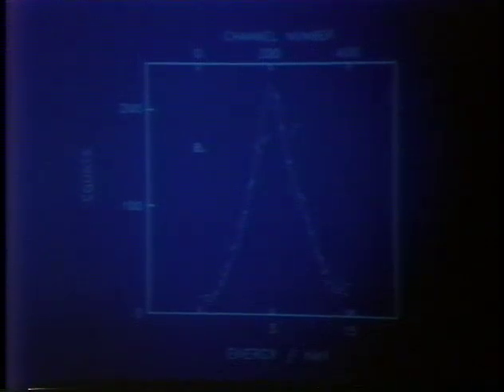So this is a scintillation spectrum, or the beta ray spectrum, of the solution, which grows in time, and is predicted by solving a differential equation which takes into consideration the accumulation as a function of the initial tritium concentration and the sampling frequency. You'll be withdrawing samples, and so you have to take that frequency of sampling into consideration. It also includes the total number of atoms of deuterium in the cell to begin with, the DT separation factor, the rate of the nuclear reaction, and of course the rate of electrolysis. And you get a curve, and from that curve you can predict the rate of accumulation, which fits very nicely to the observed result.